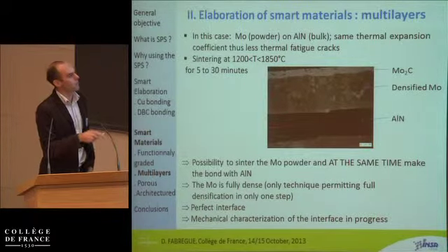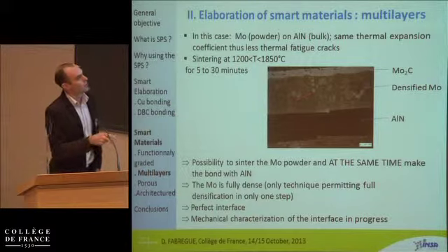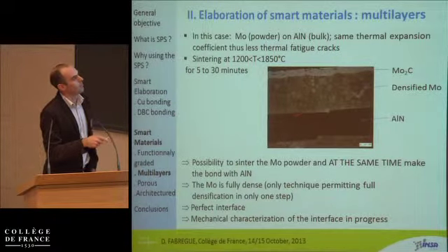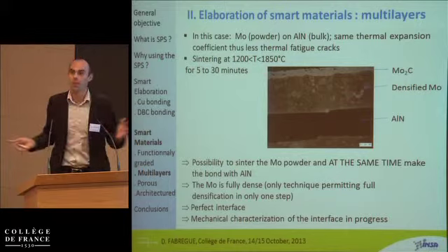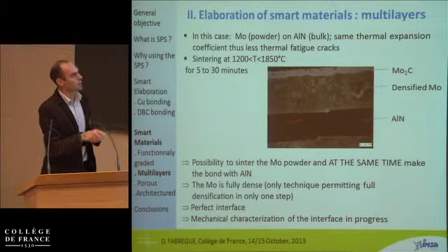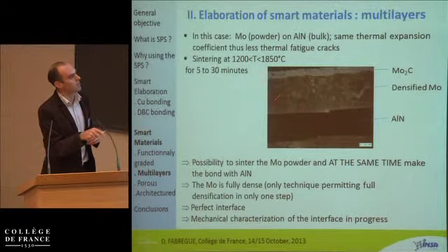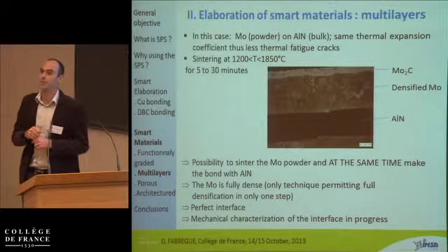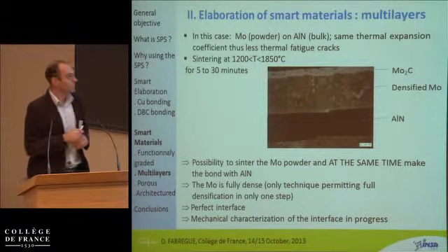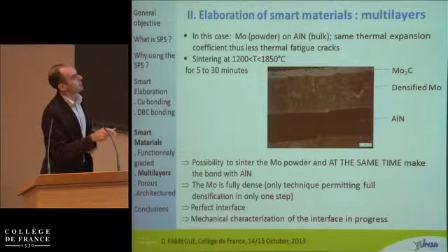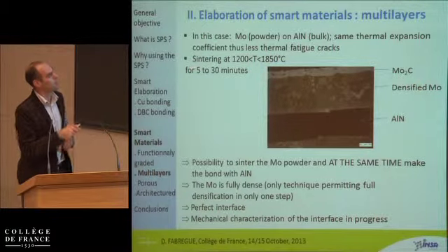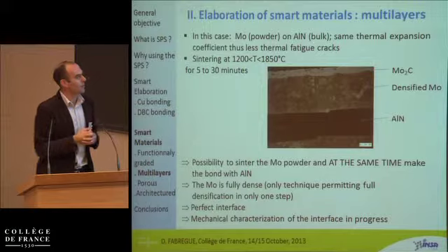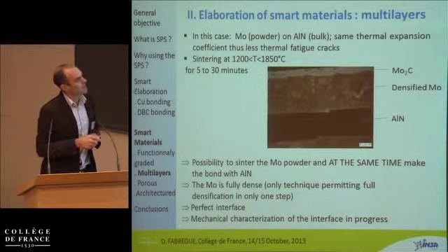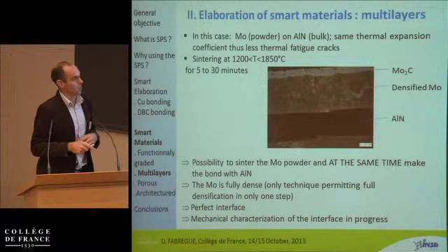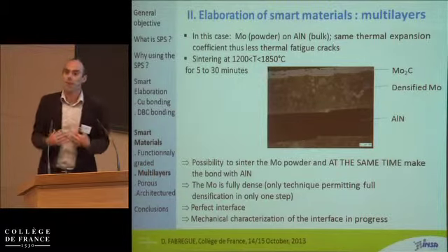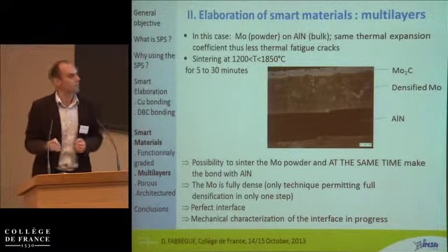So we have aluminum nitride, which is a disc, actually. We put the molybdenum powder on that, and we sinter all together. Actually, we don't sinter the aluminum nitride, but we sinter the molybdenum, and at the same time, we do the bonding between the two. So these are the parameters we use. We try different temperatures and different times to look at what the best process parameters are. The first thing, as you can see, is that you can sinter and bond at the same time, in only one process.